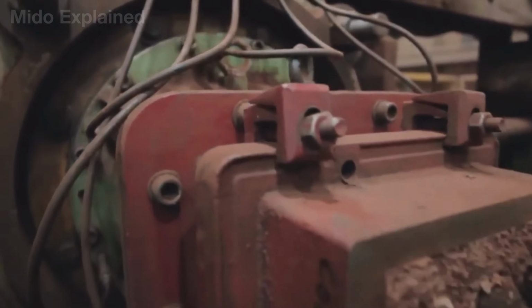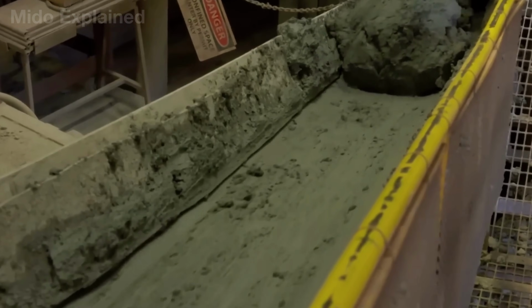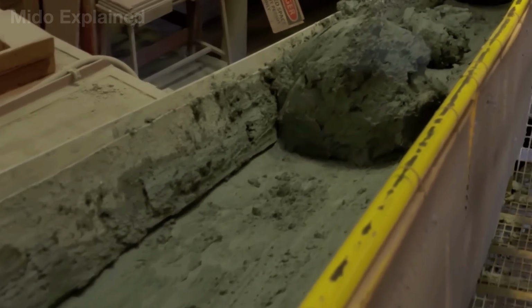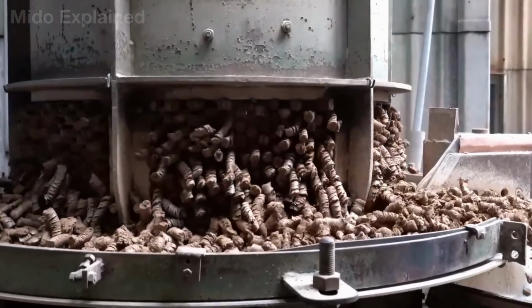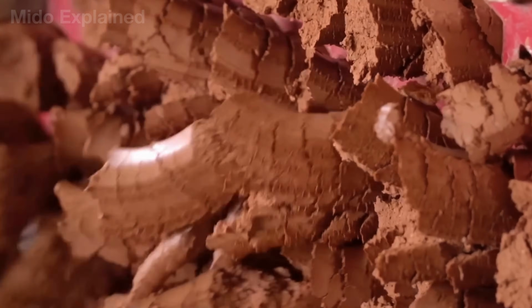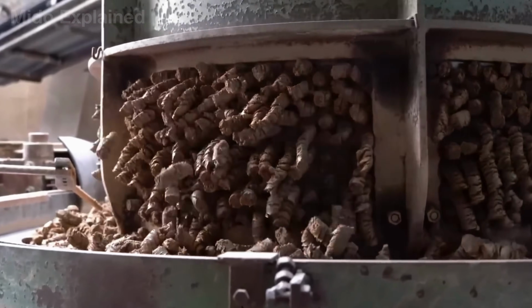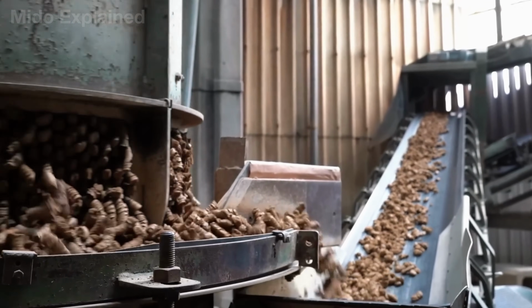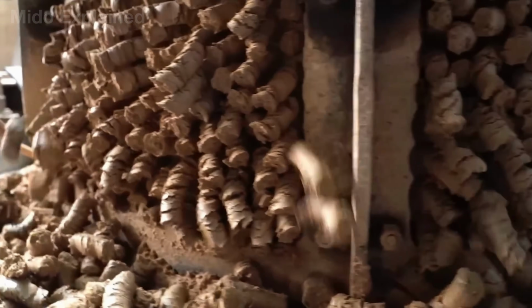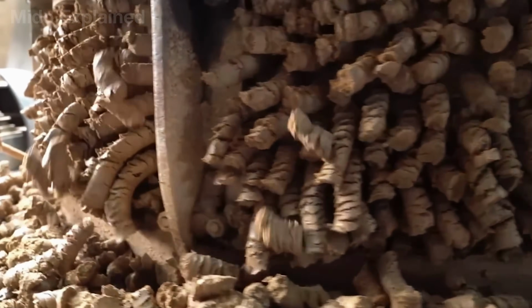Once the clay reaches the right level of plasticity, it is fed into a vacuum extruder, the heart of the entire forming process. Before being pushed through the machine, the clay passes through a vacuum chamber that removes most of the trapped air inside. If these air pockets are not removed, they can expand during firing at high temperatures, causing the bricks to crack or even break from the inside.